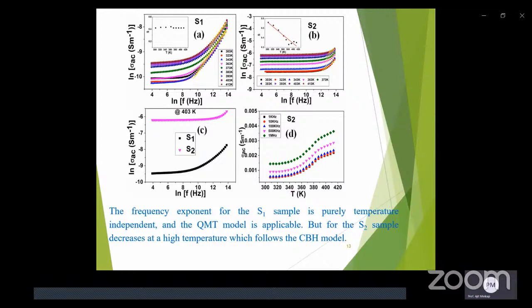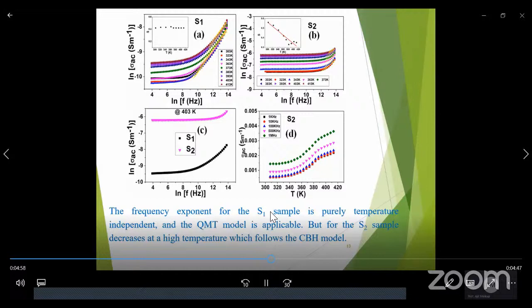The conductivity value enhances with an increase in temperature, probably due to the enhancement of free charge contribution to the composite system. The dielectric constant significantly enhances for functionalized MWCNT PVDF film over pure MWCNT PVDF film. However, the dielectric loss is significantly lower in functionalized MWCNT PVDF film compared to pure MWCNT PVDF film.